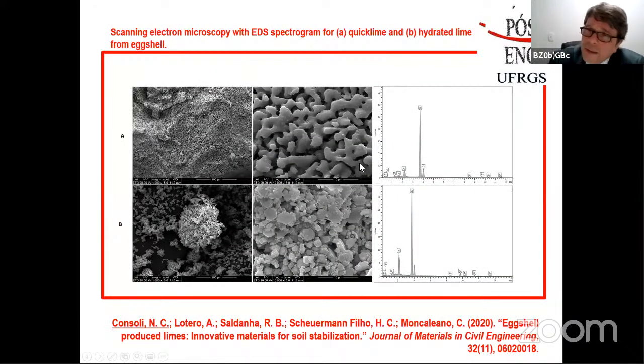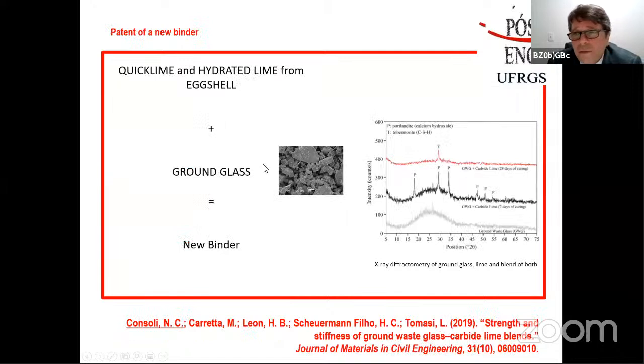So we went after that, and there is something that we published in 2020, which is the production of lime through eggshell. We have collected eggshells here, and we have produced lime from them. Here we can see some pictures showing, for example, the production of these limes. Quicklime, we have here a photomicroscopy showing the result when you have quicklime or when you have hydrated lime. It is quite interesting that we are able to produce it with good quality. And we have also produced a cement in the end, mixing these eggshell limes and other limes that are residues with ground glass.